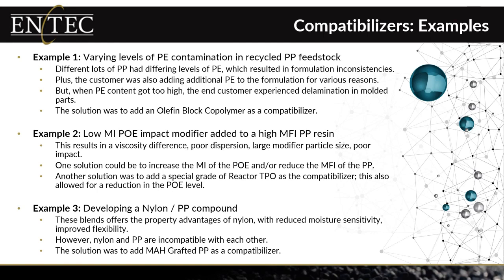It's not uncommon for customers to develop nylon polypropylene compounds. They take advantage of the properties and performance of nylon. They take advantage of the properties and performance that polypropylene can give them, especially reduced moisture sensitivity. But obviously, these two materials are not compatible at all. And once again, we're talking about a nylon compound. We're normally going to add a maleic anhydride grafted polypropylene, which will compatibilize those two polymers together. But once again, when we use a maleic anhydride grafted product, we are going to see a negative effect on the final melt flow of that compound.